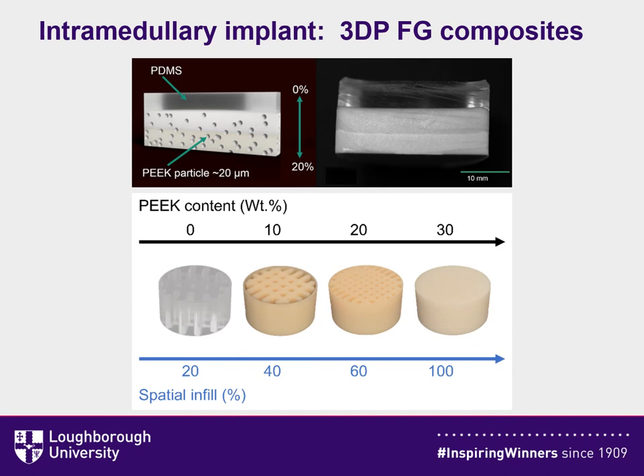In this case, we can also change the PEEK content as well as the spatial infill, allowing us to produce functionally graded composites with properties changing in a very significant range. We have also demonstrated the possibility of transition of the properties in a material which has several layers without significant interfacial areas between the layers.